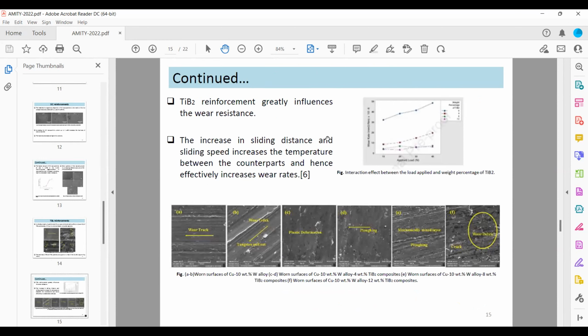The inclusion of TiB2 in the copper matrix reduces the wear rate of composite samples. The increase in wear resistance for the composite samples was attributed to the hard nature of TiB2 particles. In the wear mechanism, the reinforcements get ejected from the soft matrix and form a mixed layer. In these cases, the wear resistance increases.